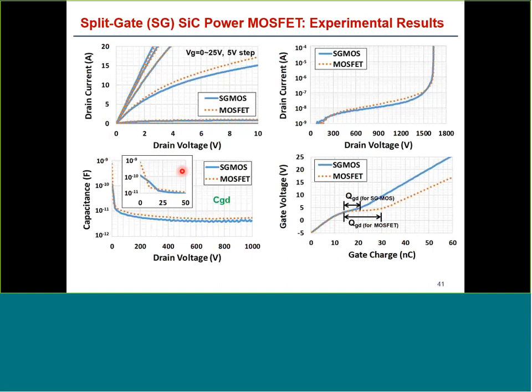So here's the experimental data on devices made with the split gate structure and the regular structure. You can see from the output characteristics that there is very little difference between them. The same holds true for the blocking characteristics, which tells us that the oxide electric field is also reasonable and low. The big improvement, of course, occurs with the capacitance.